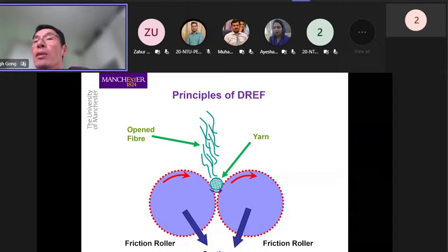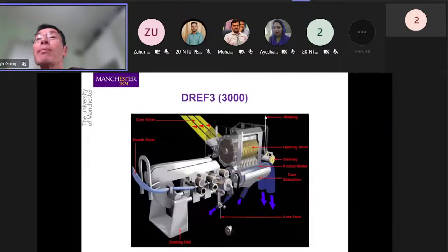But again, trying to implement that becomes hard. And this is the commercial machine. So you can see this is the Dref 3, or sometimes called 3000 as well. Essentially, you have the fibers open up, and then you got the two friction drums, and you can also feed another drafted strand, which is important because there are people who do that with drafted strand, or you can also feed an additional core filament or core strand through. So you can have one continuous strand core, one drafted core, and you have the sheath. So you can have compound structures very easily using this machine.